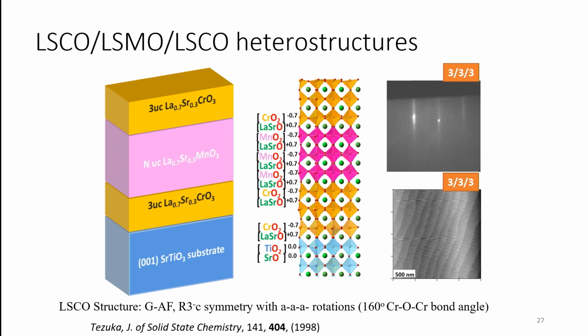So in this simple experiment, we chose to use lanthanum strontium chromium oxide. And we chose this material because chromium is right next to manganese on the periodic table. You can also use iron or titanium, but you end up with charge transfer between these other elements and manganese, which ends up counteracting what you're trying to do. But we also chose LSCO because it's an antiferromagnetic insulator.